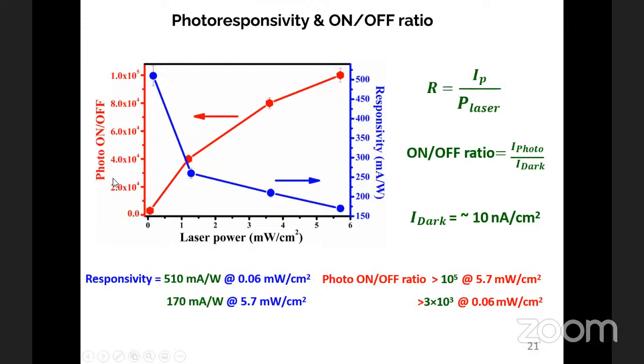In addition, you can see another interesting feature, the photo on-off ratio. The on-off ratio is the difference between the dark current and the light current when you turn the light on and off. This is very high, around 10 to the power 5, just imagine, that's 1 lakh times the photocurrent compared to the dark current. That's really interesting. So this kind of device can be an ideal candidate for most optoelectronic devices.